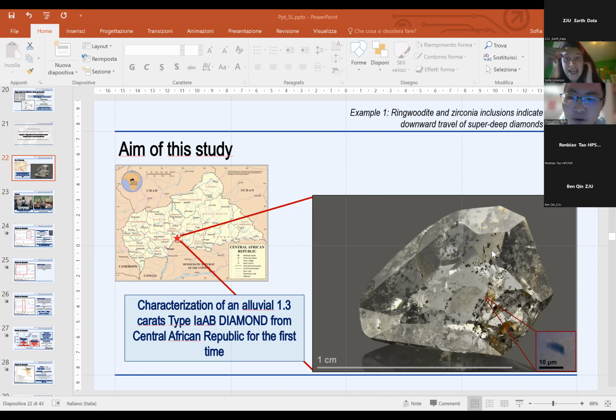With single crystal X-ray diffraction, for example, it was impossible to study the inclusion in this very big diamond. And our multi-phase inclusion is extremely tiny, about 7-8 microns. The multi-phase inclusion is this one. And we don't know precisely at which depth in the diamond this inclusion is located.